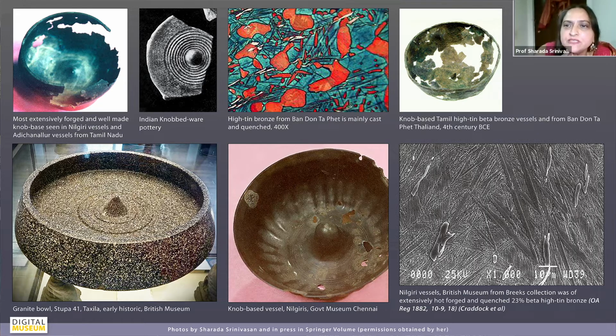You can see that it is also made by a process which is mainly cast and quenched. It's not really hot forged in the same way. A lot of the remnant dendritic pattern is still there. At the bottom is another microstructure of a bronze vessel from the Nilgiris, which is again a high-tin beta bronze, which shows extensive hot forging and quenching, because again, you see the extensive formation of this quenched martensite.